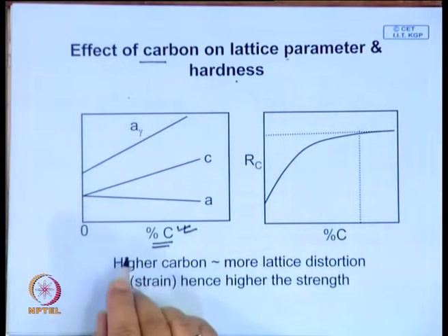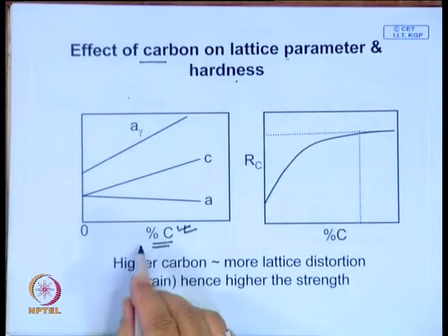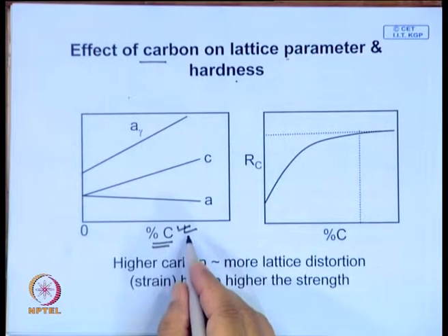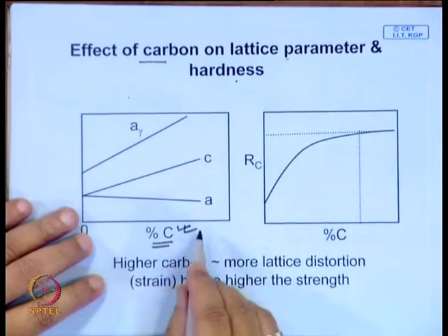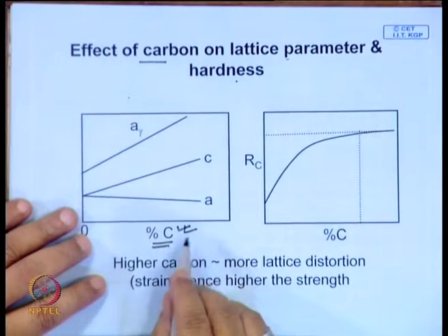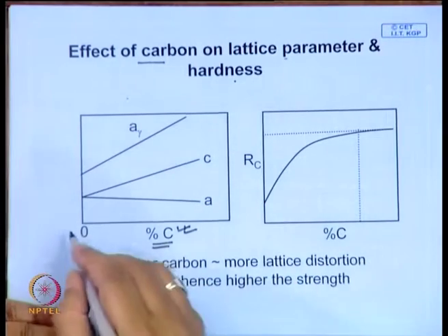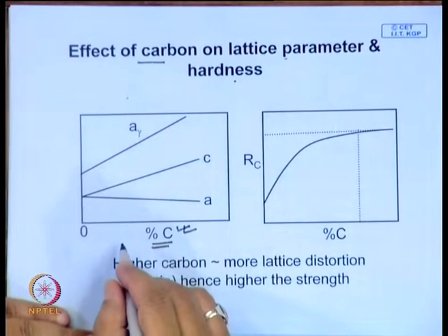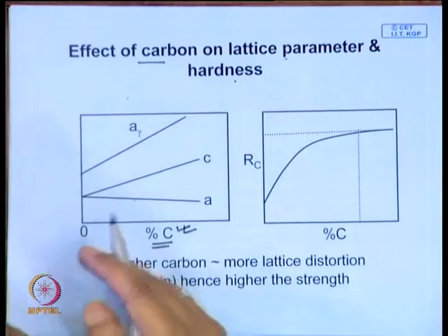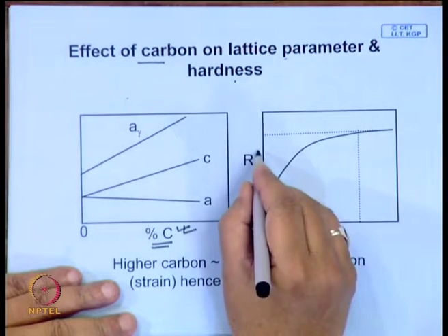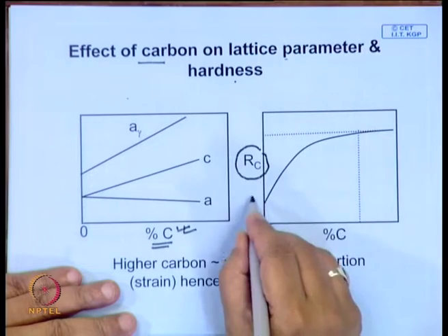So, in martensite what you have is a highly deformed structure, either plastically deformed or a twin structure, and which is submicroscopic. It is extremely difficult to see the plates or the fine structure of the plates or the laths. You can see it only under a transmission electron microscope, and the dimensions of the lath or plate, the interplate spacings, are of nanometer dimension. The distance may be several atomic layers, say 8 to 10 atomic layers. So, it is actually a nanostructure. Such fine structure, which can be seen only under an electron microscope, is definitely associated with increased hardness, which is reflected over here.